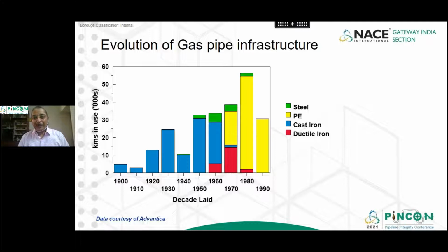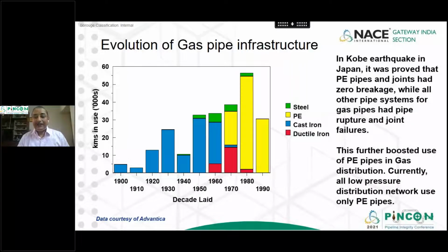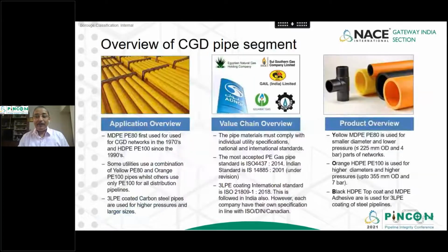There were a lot of joint leakages and subsequent explosions which took place in the UK, Ireland, Scotland, etc. And then the fully welded polyethylene system came in. By the 1990s and 2000s, polyethylene pipes almost captured the entire distribution network. In the 1995 Kobe earthquake in Japan, it was proved that polyethylene pipes and joints had zero leakage, while all other conventional pipe systems had either pipe rupture or joint failure. This hugely boosted the use of PE pipes in gas distribution. Currently, all low pressure distribution networks use only polyethylene pipes.